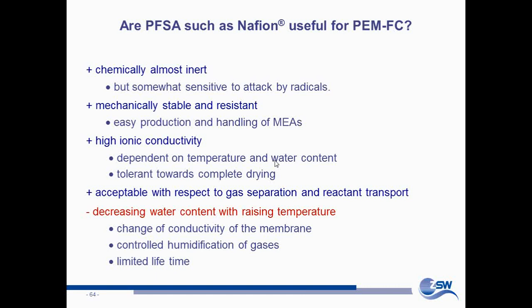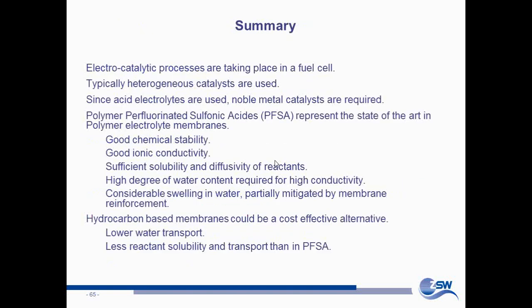They're tolerant towards complete drying, and they're acceptable with respect to gas separation and reactant transport. However, we observe a decreasing water content with raising temperature, and this changes the conductivity of the membrane, and it requires controlled humidification or drying of the gases, and this limits lifetime somehow.